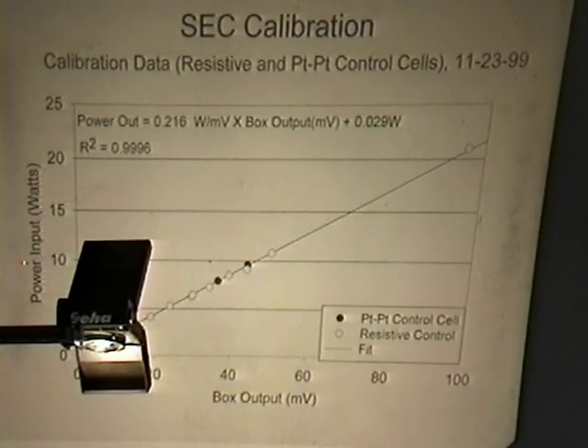Based on the best fit, the power output is equal to 0.216 watts per millivolt times the box output in millivolts, and we have this offset of 0.029 watts. Now we need that offset because we have about a dozen or so wires feeding through the calorimeter. Heat will leave via the wires, and that would be a loss of heat. So this acts as an offset for that. Now we can go on to the results.